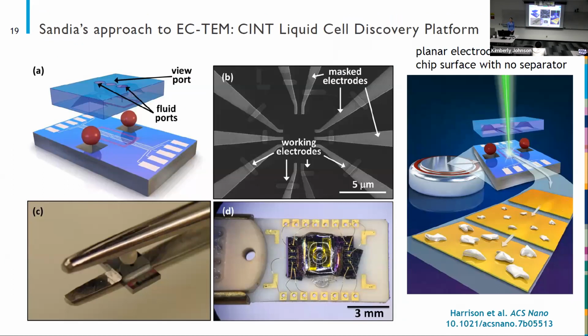And Sandia has a unique approach to electrochemical TEM. This is something that's located at the Center for Integrated Nanotechnology that we have. We created these bottom and top chips that are shown here. What we do is we have electrodes on this chip, passivate the entire bottom surface of this chip, and then we go in and use e-beam lithography to pattern smaller electrodes everywhere that we want to be able to view them, and everything else is passivated.